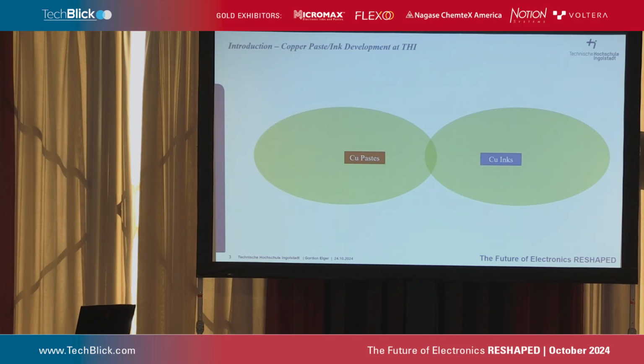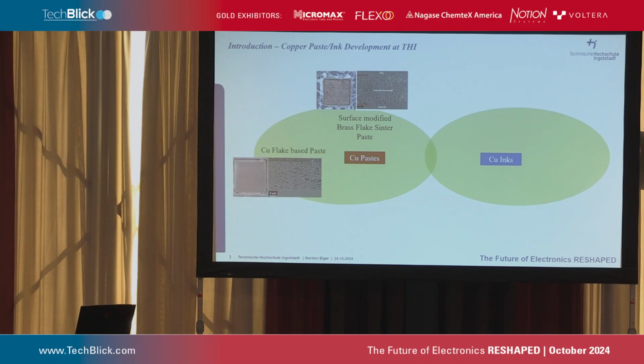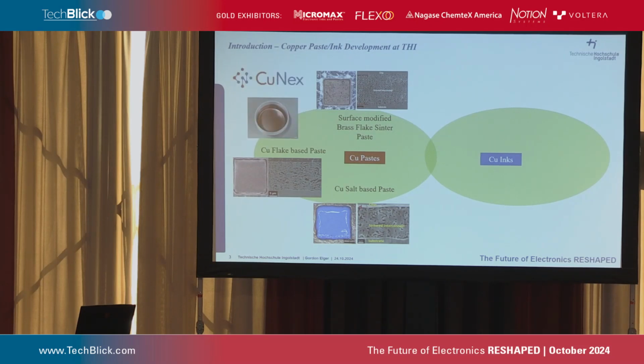We started at the Applied University of Ingolstadt 10 years ago when I started to work at the university with the development of copper sintering paste. So we started with using brass flakes, actually etching away the brass, putting them into a binder and using them for power electronic for sintering. Then we changed to pure copper flakes, but initially we worked on copper salt-based paste. We did a lot of mistakes before we then got inks really working. Actually, we founded a company, CuNex, in 23, which is now selling those copper flake-based copper sinter materials mainly for the booming electromobility sector, for power electronic inverters.